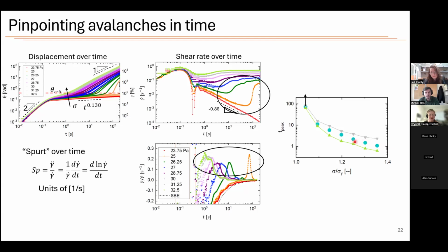And so as we approach the yield stress from above, where a value of 1 here would be applying exactly the yield stress, we see the time it takes to reach the avalanche increases very sharply, where we would expect this to basically diverge. So it can take longer and longer for the material to start to flow. And so this is again compared to our 5.7 seconds. It's clear that if you have enough stress, or equivalently enough ketchup in the bottle, then you're going to very safely get ketchup to flow within that time scale. If you have less ketchup, then it can take much, much longer for the ketchup to flow.